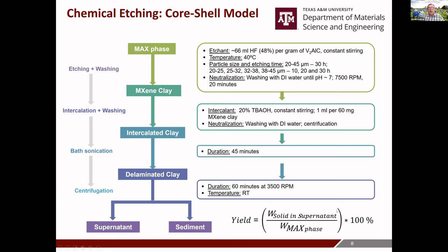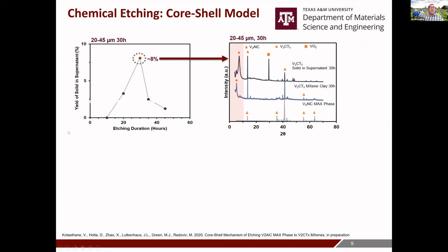And for practical reasons too, because in many cases we will really want to get single or few-layer MXene instead of using MXene clay. So when we look at this yield of solid, we see that it is a very strong function of etching time and particle size. Small particles give us practically almost zero yield, and with increasing etching time, we are getting a maximum somewhere around